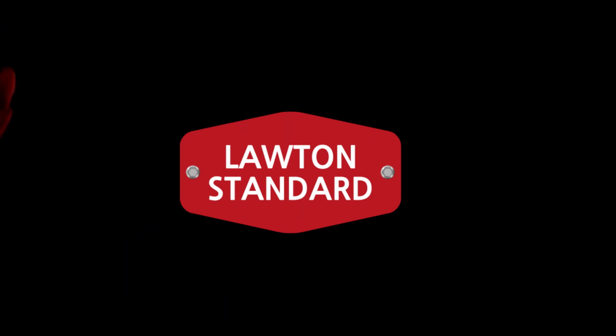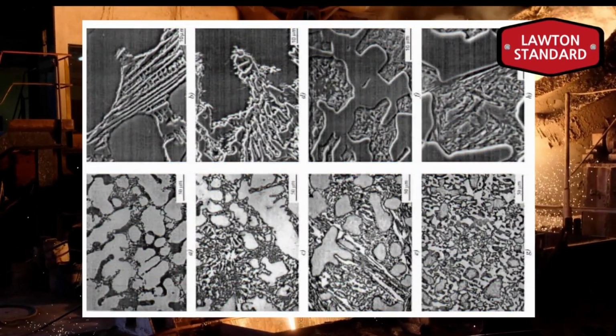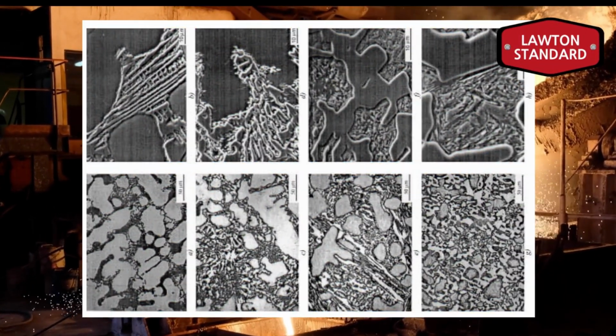The reason why it's so crack sensitive, or lacks toughness, you could also say, is the exact reason why it's so abrasion resistant, which is that those carbides, because they have such a high hardness on a micro scale, have no ductility, nothing, right? So it's really easy to brittle fracture them. But at the same time, it's also really hard to get something else that's hard through it.